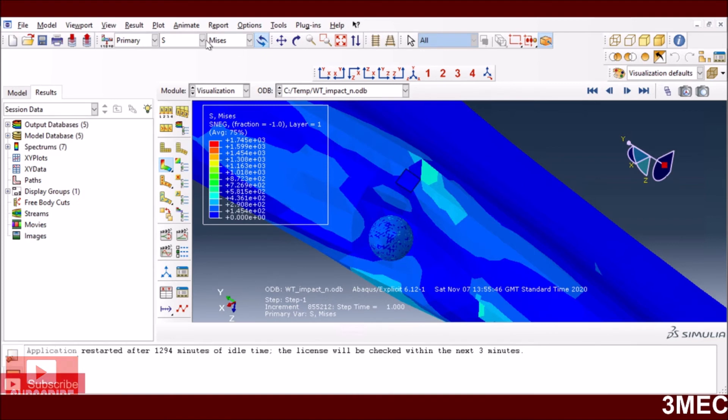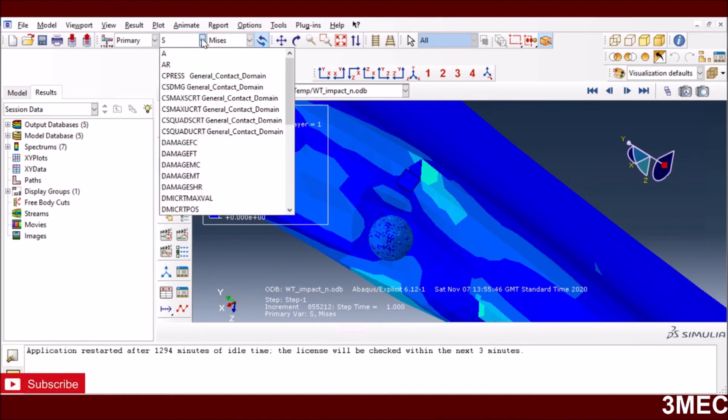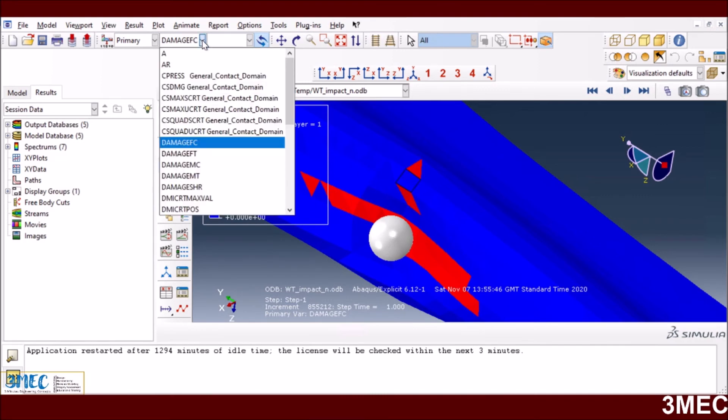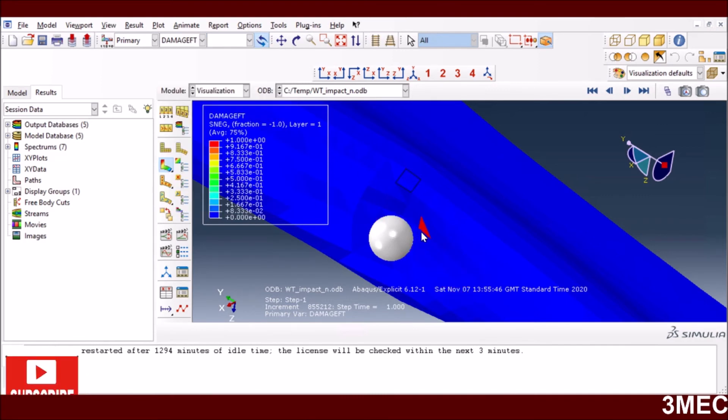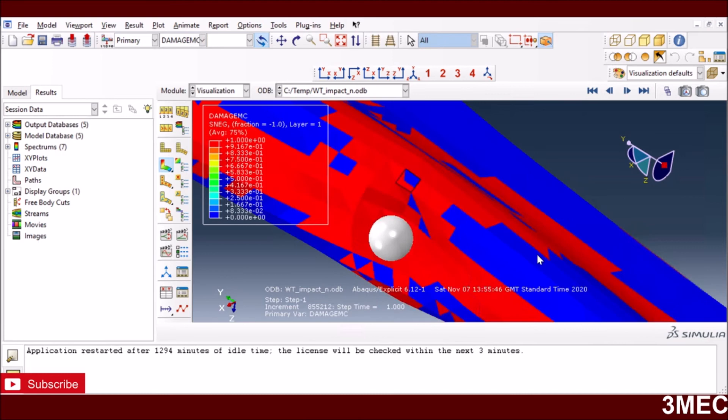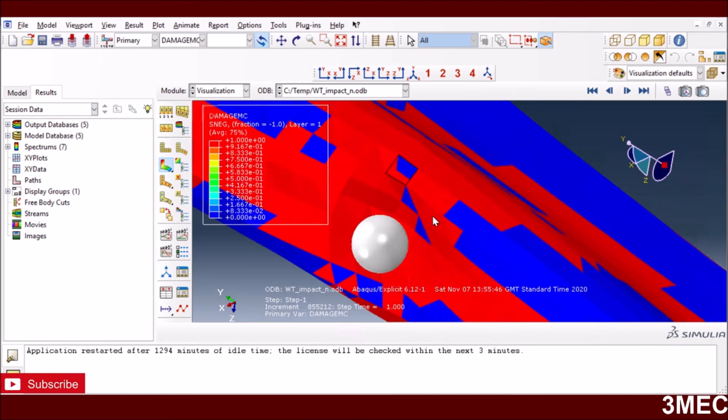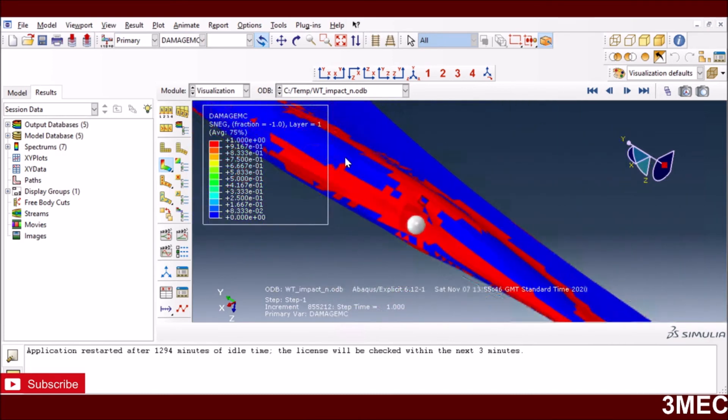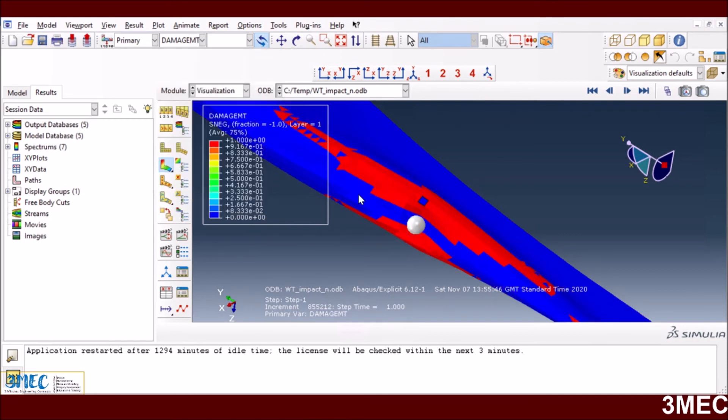I'll show you the animation at the end. If I want to plot different types of damages, I can see damage in fiber due to compression - it's failing in compression in this area. This is tension, so some areas are in tension. The mesh needs refinement but this is okay. Matrix under compression - you see matrix is pretty much damaged because you have huge indentation or deformation in your blade since there were no internal structures, stiffeners, or spars. Under tension also, these are failing but not all. Then shear type damage as well.